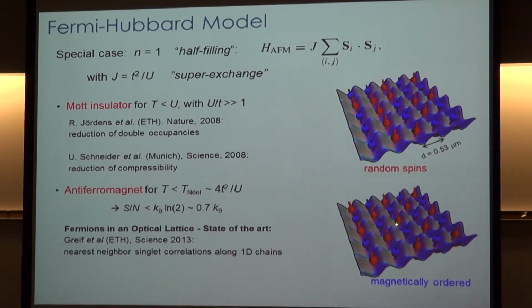Now, for an antiferromagnet, if we can get down to this superexchange energy, then you see the difference here. We're still in a Mott insulator, but now we have spin ordering. Now it looks like a checkerboard. Now you have up, down, up, down, up, down, up, down. And you have to get below the spin degeneracy, which is log 2 per particle, in order to go from this Mott insulator to an antiferromagnetic Mott insulator. So this temperature, the Néel temperature, is considerably colder than the transition temperature to the Mott insulator. And so that's the challenge: how do we get to lower temperatures to be able to see this ordered phase?